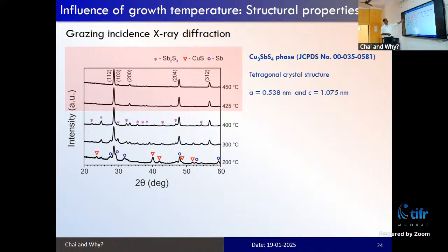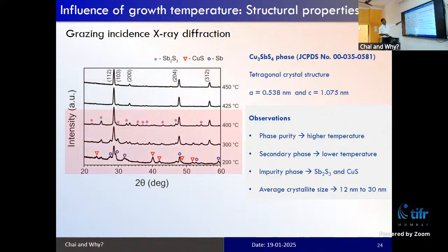If you grow above 400 degrees Celsius, you get cleaner, phase pure Cu3SbS4 thin films. So as you can see, the higher temperature gives you the phase pure copper antimony sulfide materials. At a lower temperature, you have impurity phases like antimony sulfide, copper sulfide. There are binary and ternary phases which appear at the lower temperature. So higher growth temperature gives a better crystallinity.